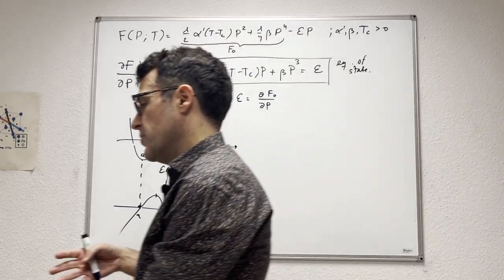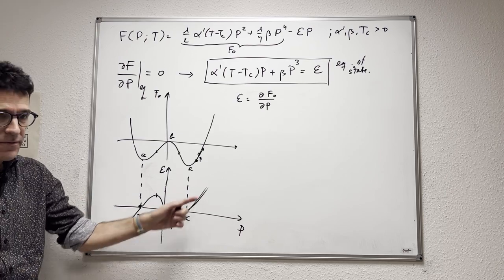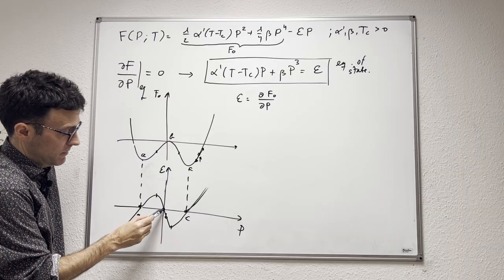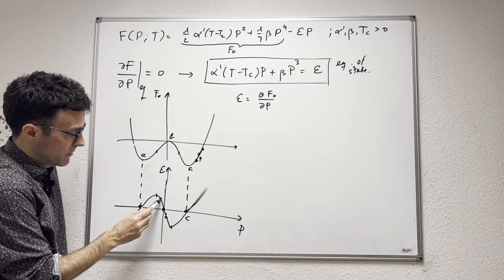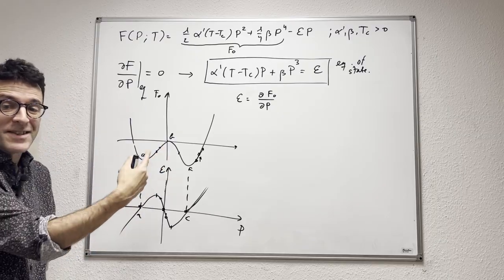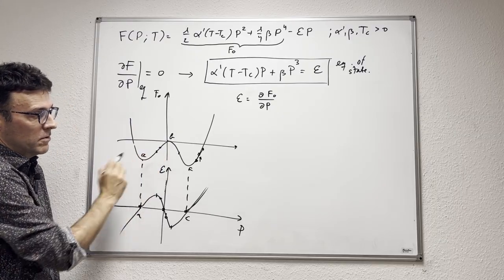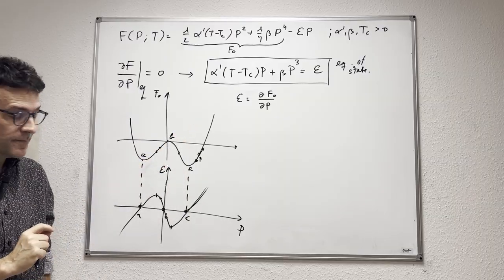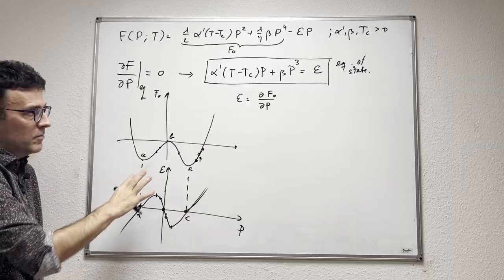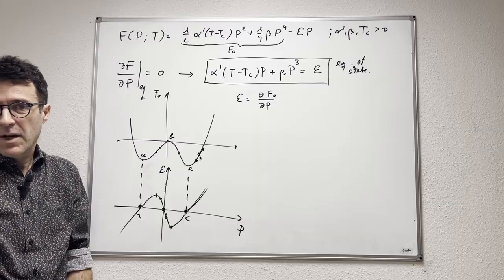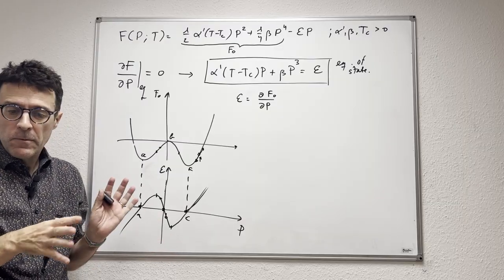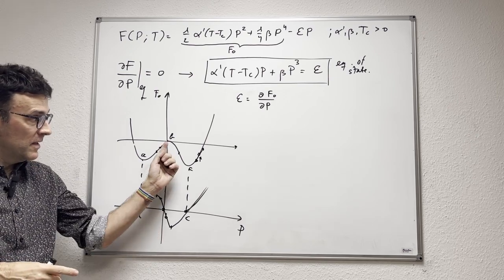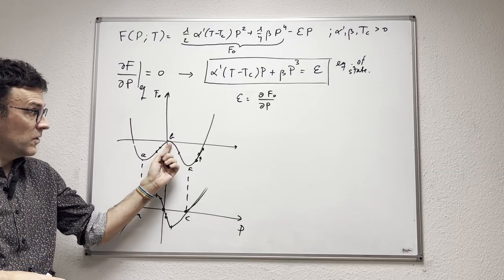All right, but that's not the whole story, because this curve might invite us to think that if I apply a zero field, for example, here, or if I apply a field like this, I could stabilize my system with a polarization equal to 0 or this kind of polarization at the temperature in which it presents this kind of free energy. Okay, and that's not true. This condition is an equilibrium condition, but we have to introduce an additional consideration to identify the situations that give us a stable equilibrium. So if I apply zero field, this state corresponds to equilibrium, but it is unstable equilibrium.